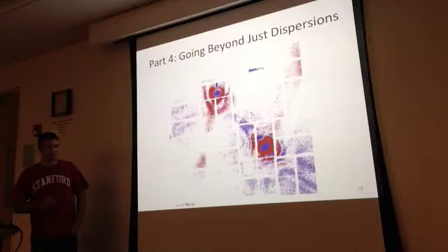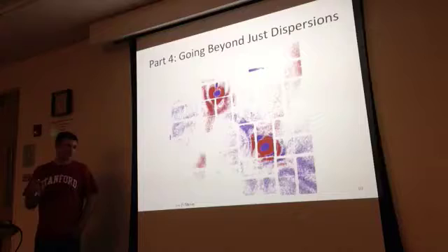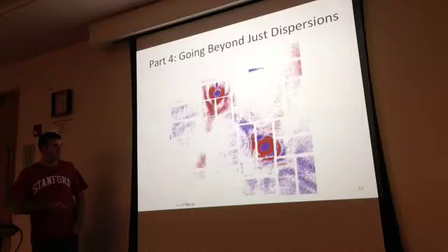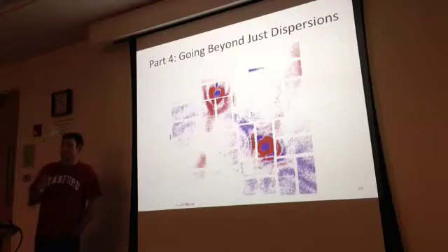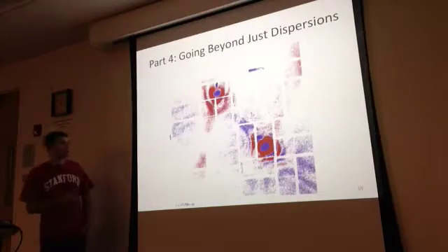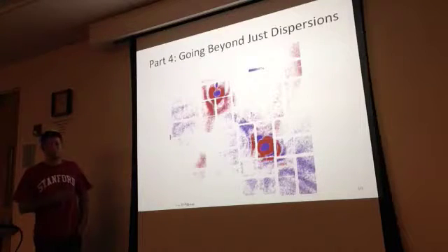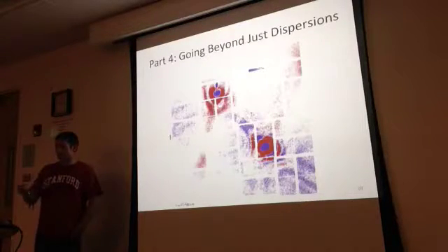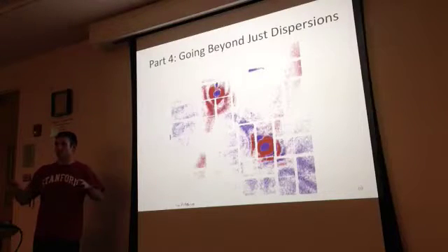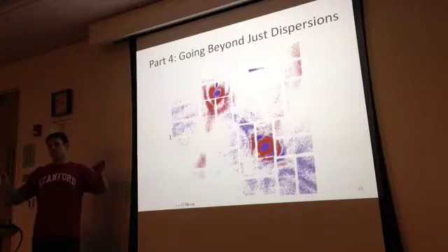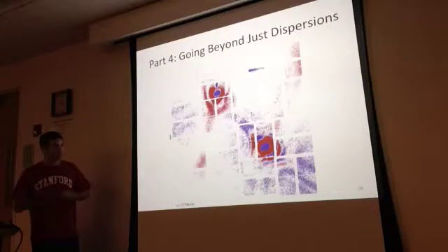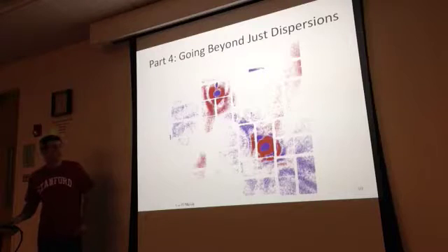So if you can imagine exciting only a small subset of the phonons, say in one region of the detector, then what you might hope for is you strike it with a laser pulse, this small subset starts oscillating like crazy, and then you can see that other modes on other parts of the detector that this thing you excited is coupled to start to show some activity, not right when you hit it with the laser pulse, but after some time, as energy transfers from the modes that you excited to its target decay modes. And that's basically the experiment I'm going to show you.